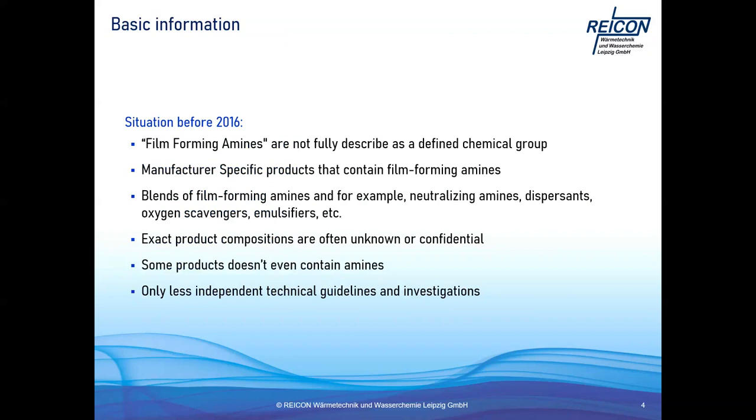So it's not a defined chemical group. There were a lot of manufacturer-specific products on the market which do contain film-forming amines, and also were blended with neutralizing amines, with dispersants, sometimes oxygen scavengers, and there were even products called film-forming amines which don't have any amines in them. So the exact product composition was often unknown or confidential, so there was less knowledge and less international or independent guidance on the use of these products.